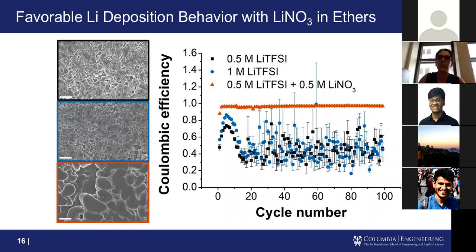So we wanted to see, could we do this in maybe another solvent system? Another popular solvent system for lithium metal batteries is these ether solvents. I showed you on one of the earlier slides that ethers are much more stable at lower potentials. So they should lead to better lithium deposition behavior. They shouldn't decompose as much, and you should get a better SEI. But what actually happens in practice?